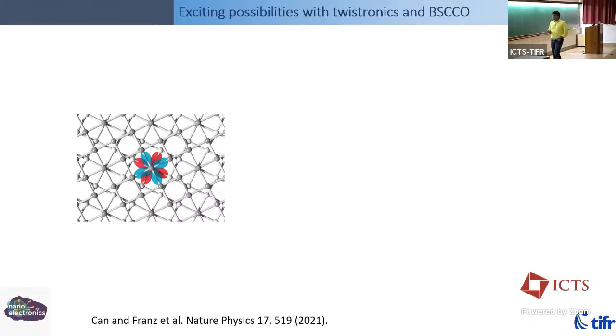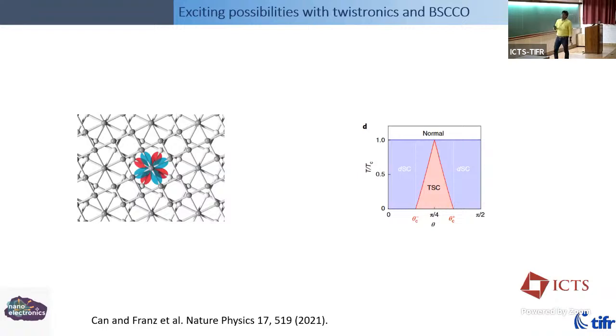So there was this work which basically theoretically proposed that if you twist two layers of copper oxide plane, or BSCCO, by 45 degrees, then you could get some interesting physics. Namely, their key prediction is that when you twist it by 45 degrees, you get a kind of topological superconductor, which breaks time reversal symmetry, and it's like a D plus iD kind of superconductivity at the interface when you twist it. And the idea is that there is a co-tunneling of Cooper pairs across the superconductor.